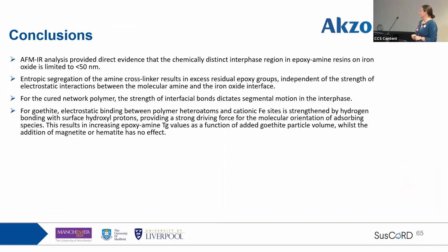So that's the end of my talk. The conclusions here are, first of all, that AFM-IR analysis provided direct evidence that these chemically distinct interphase regions are very, very small in comparison to what's widely been quoted in the literature. They're less than 50 nanometers. We can't really resolve them with the AFM-IR, we can just detect that they're there.